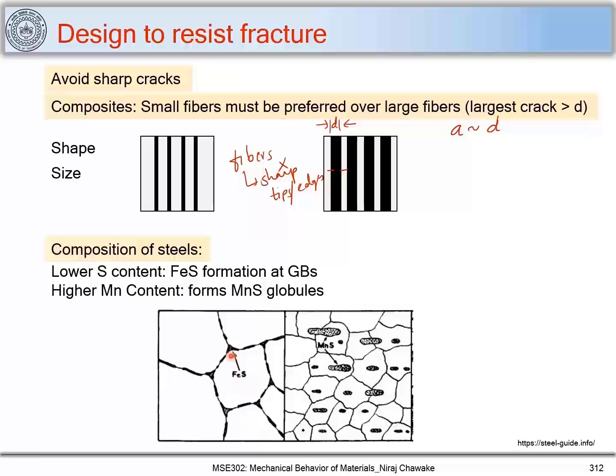And you might be remembering the case of Titanic. When the Titanic was made, it had supposedly a large content of sulfur. And because of this sulfur content, there may be a formation of iron sulfide at the boundaries. And when it hit the iceberg, this material caused crack formation at these boundaries and it catastrophically failed, and that led to a tragic accident.